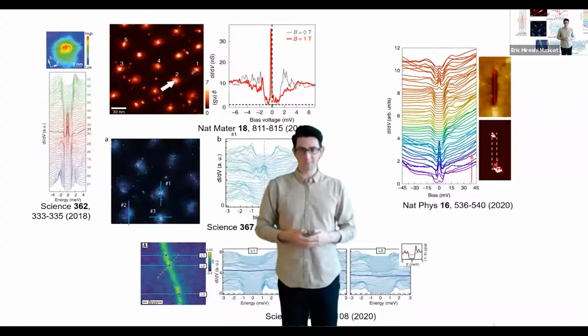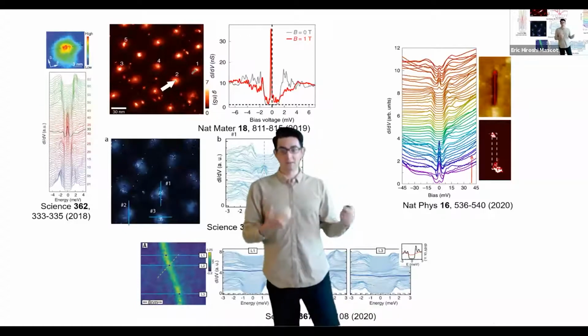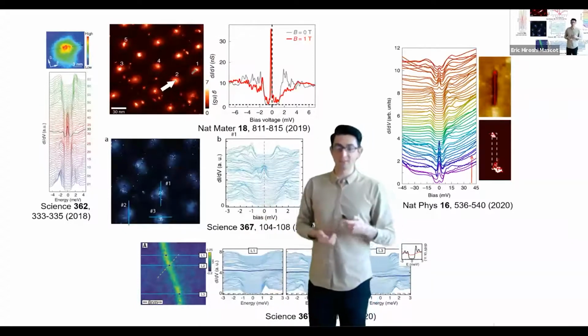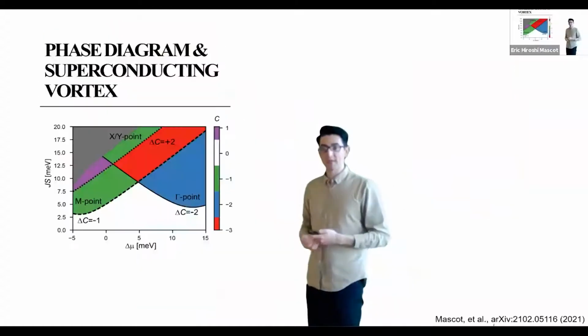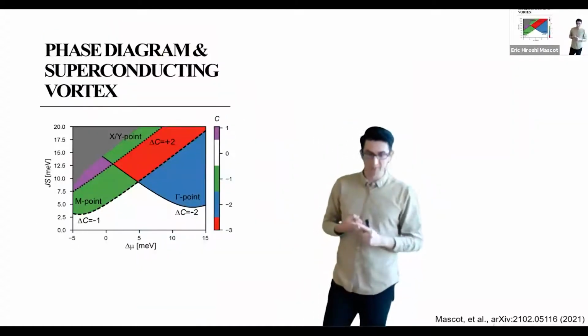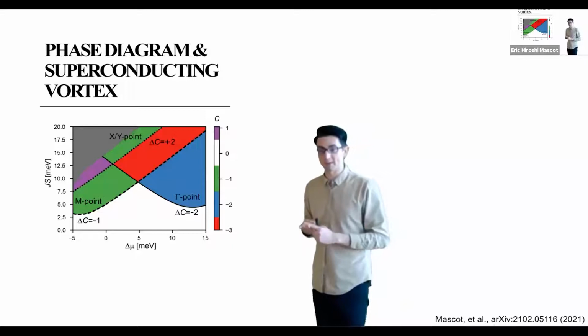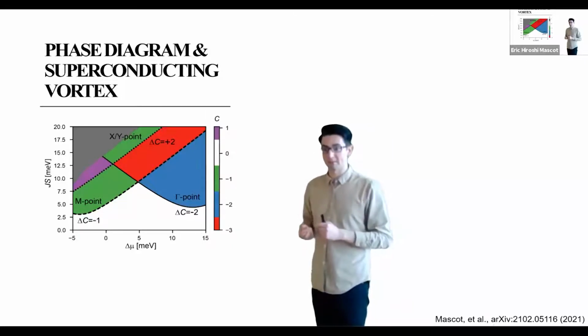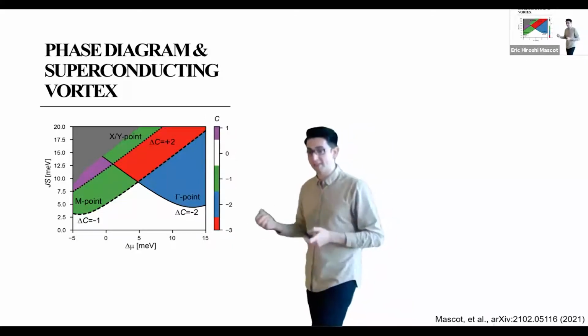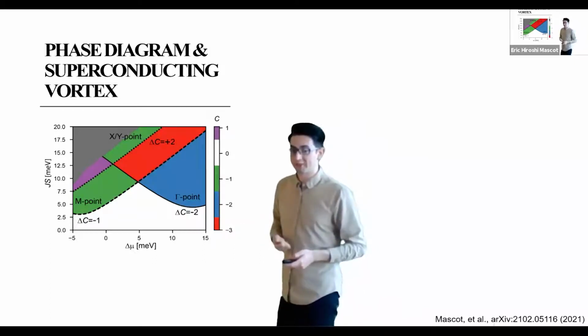So now we have those three ingredients that we need for topological superconductivity. And so we took a model for FeSeTe, and we added those surface effects, the Rashba effect and the magnetic ordering on the surface. And indeed, we find topological phases for this material.